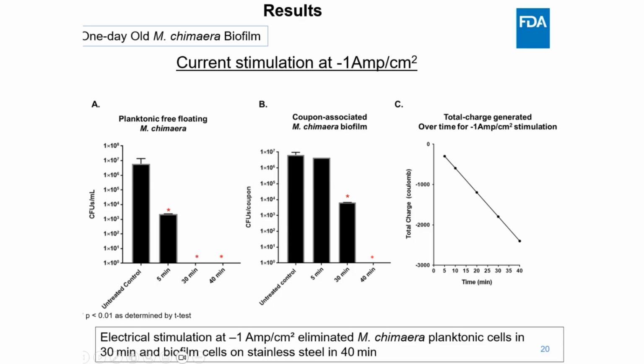An increased amount of cathodic charge was delivered throughout the stimulation period, as you can see in figure C. So these results highlight cathodic current as a promising non-antibiotic strategy for disrupting both early stage biofilms and also planktonic NTM populations.